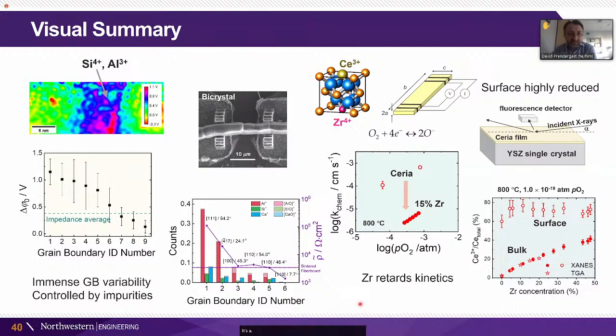It's an interesting catalytic system to think about, because we've studied this in a different context and noticed that you can dope your surface with atoms like platinum or others. There's lots of single atom catalysts that can be supported on Ceria. And those single atoms have this ability to alter their oxidation state, because anytime they want, they can exchange electrons with the substrate. And it will absorb them quite easily. So you can start with platinum as a dopant, as a substitute, let's say in 4+. Next to a vacancy, it becomes 2+, which means it eats 2 cerium polarons. And then as you do your reactions, it goes back and forth between 2+, 3+, 4+, all the while sometimes exchanging with the Ceria, sometimes not.